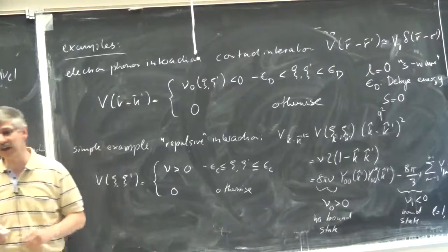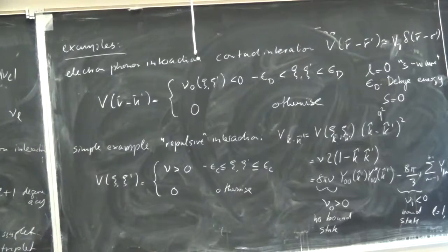But when we have strongly correlated electron systems, these mechanisms do not work in many cases, so these energy scales are not necessarily so different, and then you have to escape into another channel. But of course, when you go into higher channels, then this often goes just down in the critical temperature, except, for example, in the high temperature superconductors, of course, for different reasons.